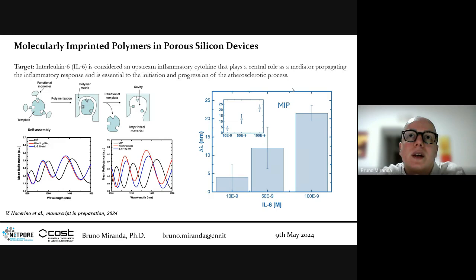The approach is to detect its presence in artificial serum using molecularly imprinted polymers. Basically, here we have a polymer specifically made to interact with interleukin 6. Then we have template removal, and the final result is a polymer that has the typical shape cavity of interleukin 6, for example.